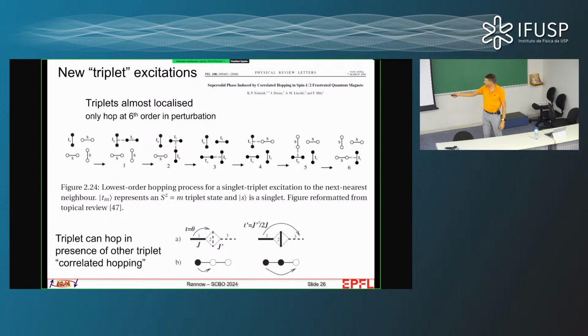But because of this orthogonal orientation, in lower order of perturbation theory, nothing happens, and you actually have to go to 6th order in perturbation theory before you can have any movement of these excitations. So you get very localized excitations, which is simply a local triplet that sits there.